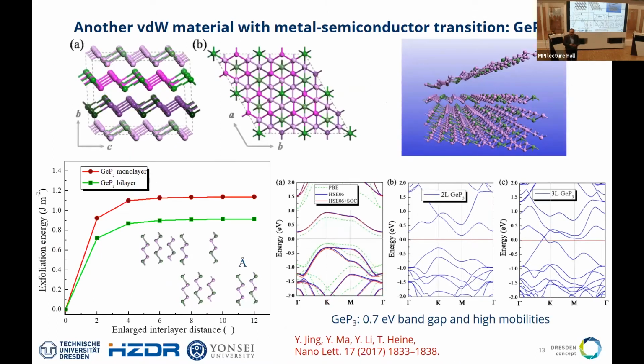Black phosphorus is another one, right? Black phosphorus is really loved by device people, just as it is hated, because if you expose it to oxygen, it will just corrode away. So you can stabilize that by putting in germanium. And that phase is known from experiment for decades, right? GeP3, you can find it, that's the bulk structure.